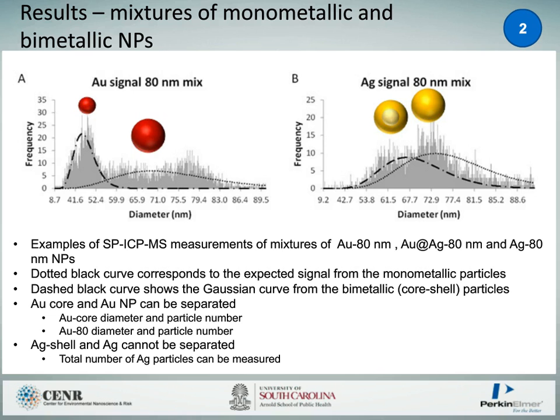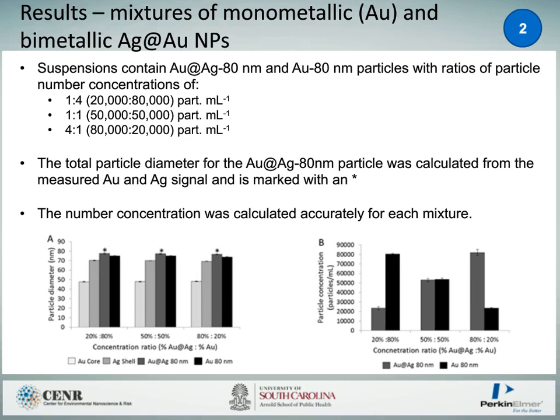You can see on the left-hand side that we're able to separate the monometallic particles from the bimetallic particles because of the size difference. And on the right-hand side, we're not actually able to see the difference between a large particle and the shell of the silver nanoparticle. So here's one set of results that we have. Again, this is coming out as an application note soon, so there's more details in that.